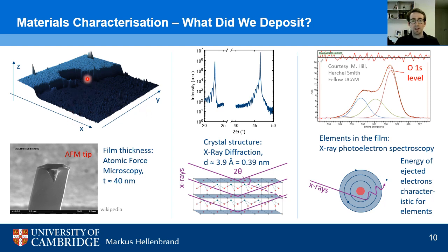If you remember, the thickness of the oxide determines how many electrons can get from one side to the other. So we have to make sure that the film has a well-defined thickness, which is the same throughout our samples. Furthermore, if we had a large surface roughness, it means from one place of the film to the next one, we would have large differences in thickness, and again, we would have very different behavior from one device to the next. And this is bad because we want uniformity and reproducible behavior.